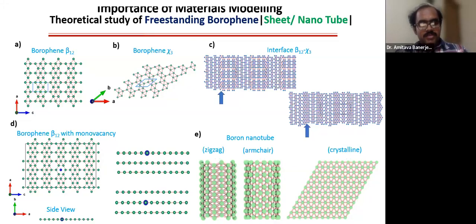Next, if you remember, Dr. Negi has shown that we have synthesized boron nanotubes. As I said, there could be different polymorphs of borophene. Here we have studied what kind of phases can form what types of nanotubes. If you remember our graphene analogy, in graphene we found that we could have zigzag and armchair, depending on the rolling of your sheet. Here again, sheet means we have different types of sheets corresponding to different phases. That could give you different types of properties in your nanotube.